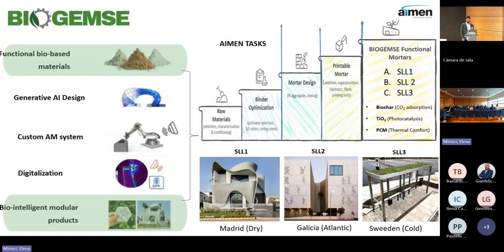And for the next phases, the idea is to adapt the mortar to 3 different solutions. And in this phase, the functionality becomes important. So the idea of the project is to obtain 3 different products with 3 different functionalities. One of them is CO2 absorption. This will be given by the addition of biochar. The second one is photocatalysis to remove pollutants in air. This will be given by the addition of titanium dioxide. And finally, to induce thermal comfort properties by the addition of phase change materials.